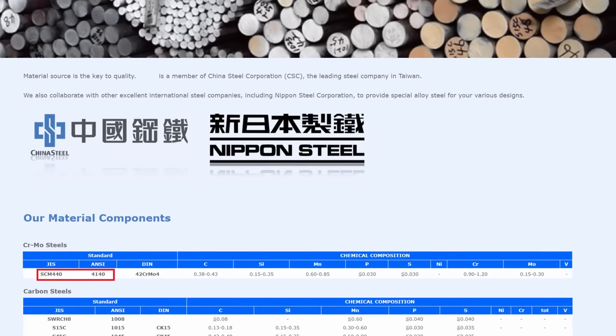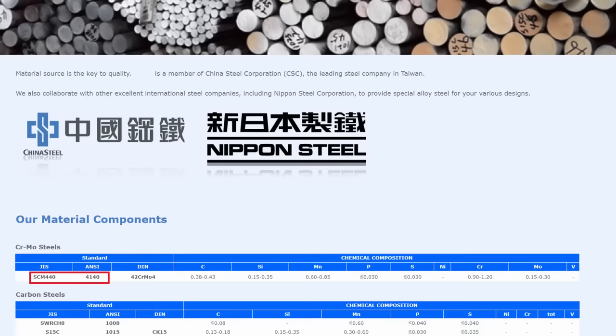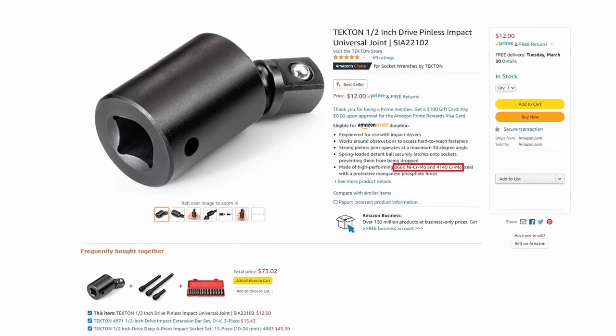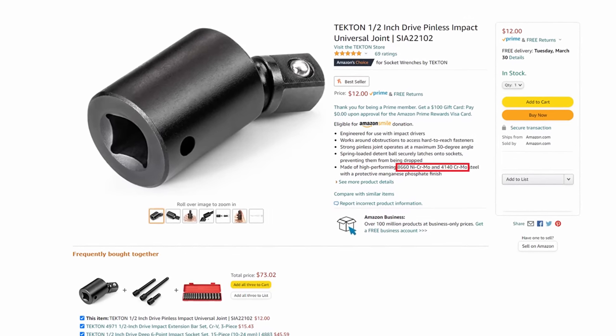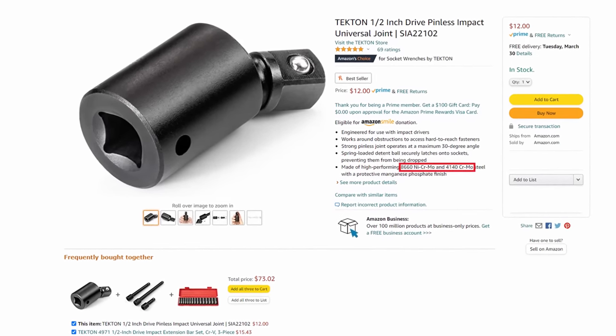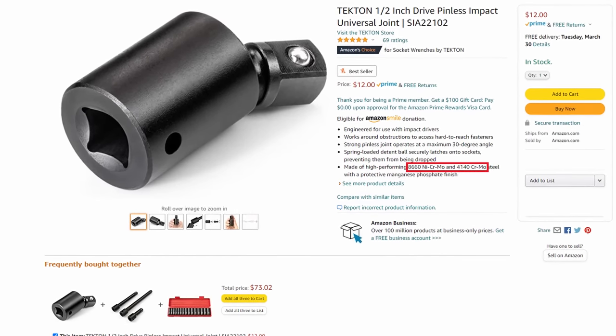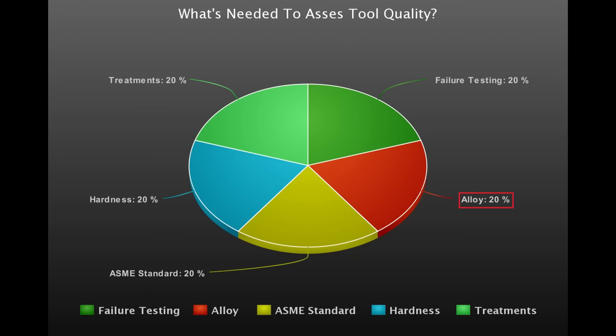Or as we call in the US, forty one forty. The only slight difference being among all of these pieces and adapters is the Tekton, who calls out forty one forty as well, but uses eighty six sixty for the ball drive end, which is a chromoly, but it's a nickel chromoly. So that's a piece of the pie that's more or less covered.